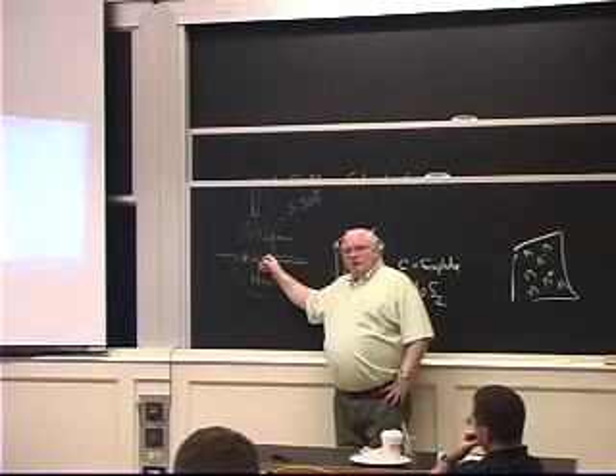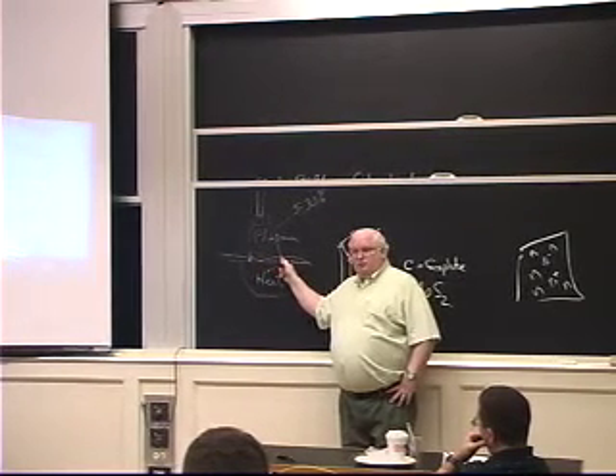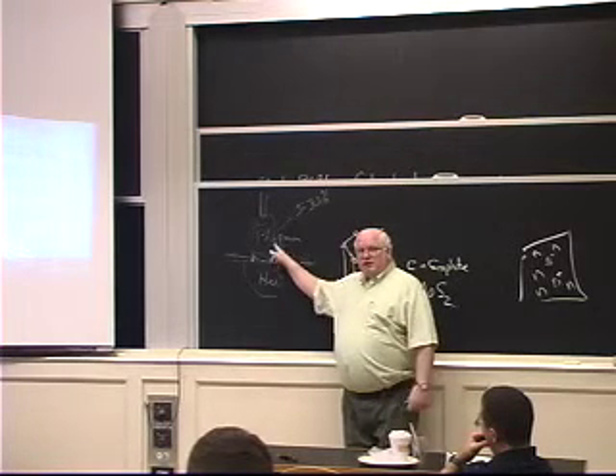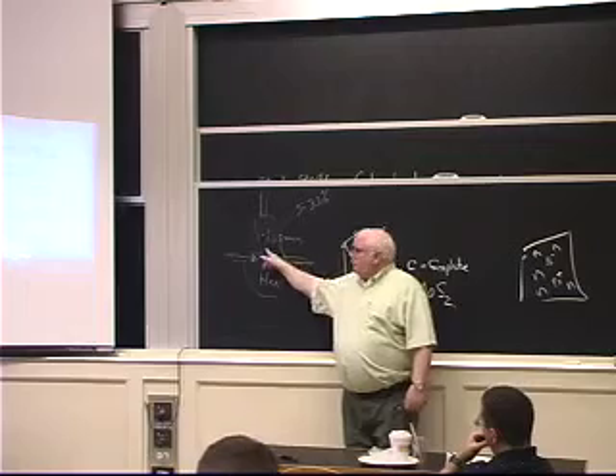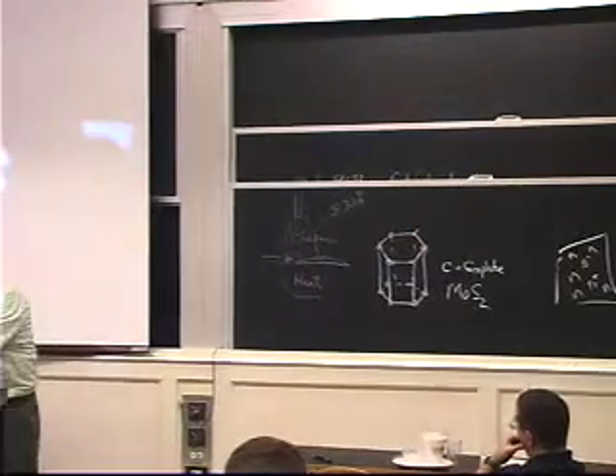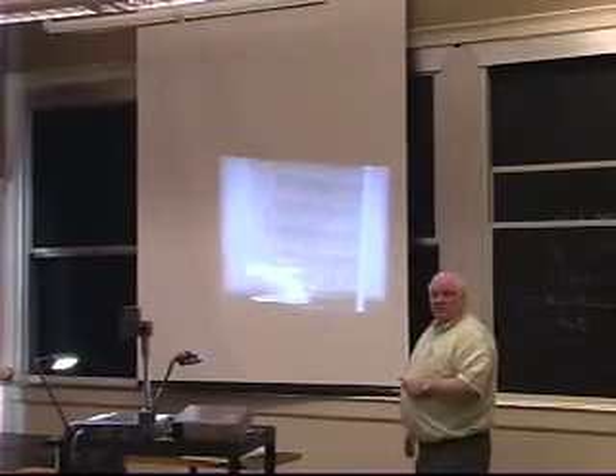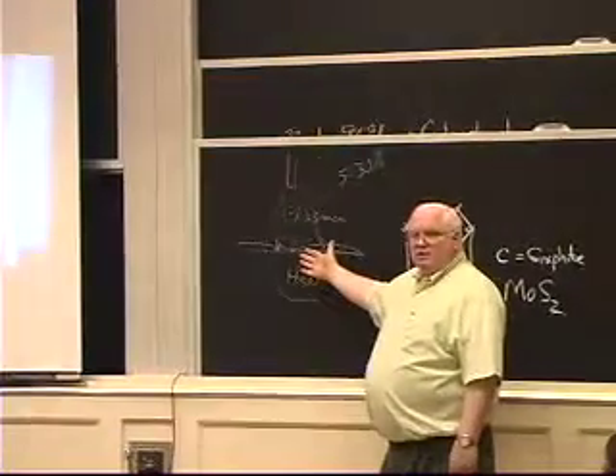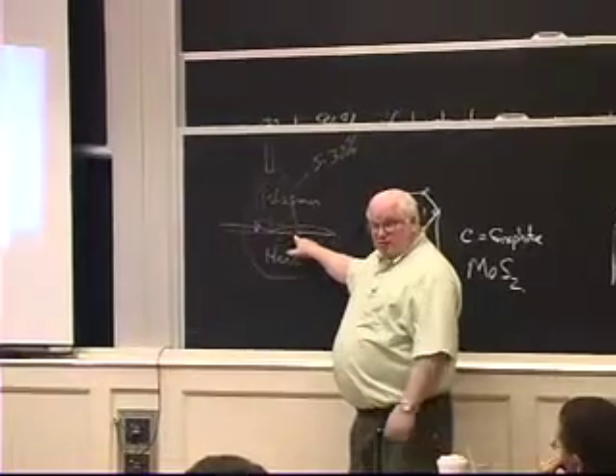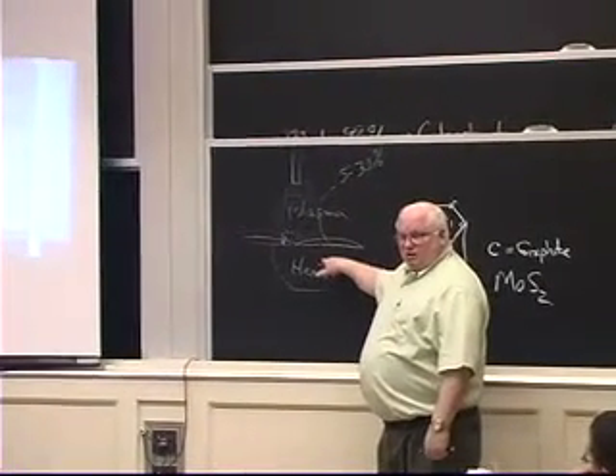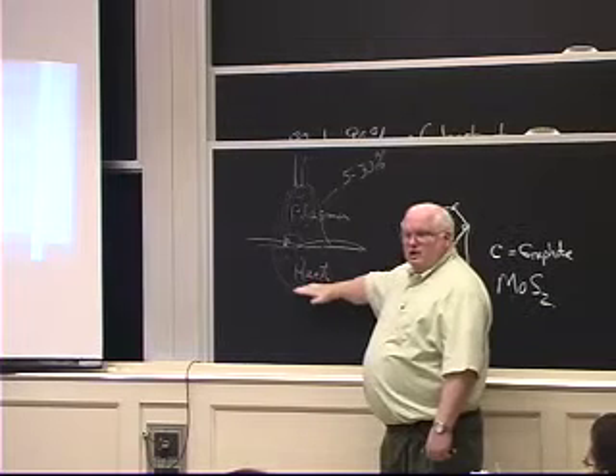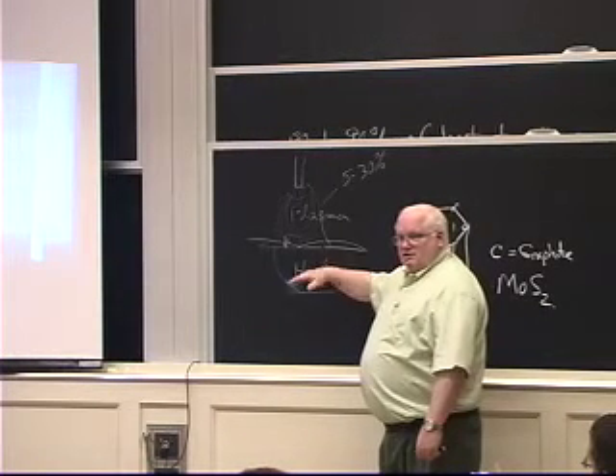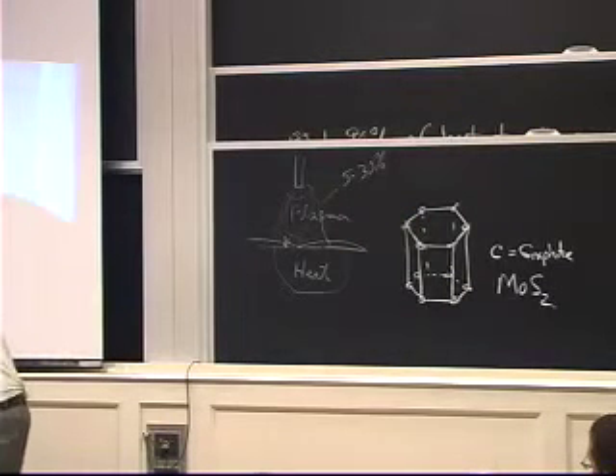Then they're accelerated across here. This is sort of a rarefied space charge region. I mean, this is mostly neutrals. There's not enough electrons in here to carry the current because it's cooler. It's only 3,000 degrees, not 10,000 degrees. Go back to Elenbaas-Heller. Okay, if I go back to Elenbaas-Heller, at 3,000 degrees I don't have any charge carriers. So the electrons have to punch their way through that thermal boundary layer of 10 or 15 thousandths. To do that, they have to pick up a big voltage, a big electric field, and that energy gets deposited in here. But in addition, they decay down to the Fermi energy of electrons in the metal. And that's this whole heat transfer that I talked about yesterday.